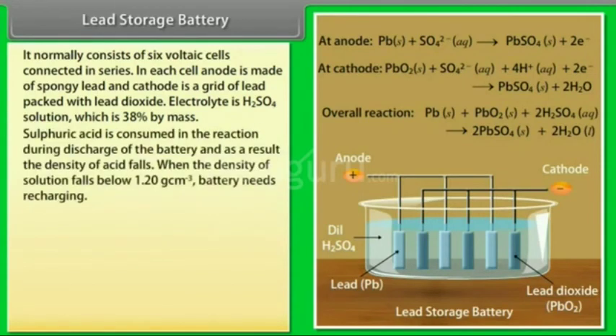Sulfuric acid is consumed in the reaction during discharge of the battery. And as a result, the density of acid falls. When the density of solution falls below 1.20 gram cm raised to the power minus 3, battery needs recharging.